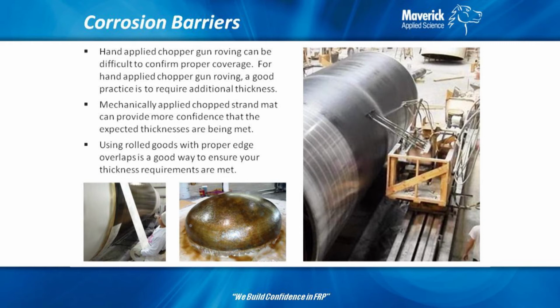If you decide to allow mechanical applied chop or even hand applied chop, it's not uncommon to require your vendor to add on a percentage, say 25%, to that corrosion barrier to ensure that you're getting the thickness of the corrosion barrier you want. So if they want a hand chop or mechanized chop, it's common to increase the thickness of the corrosion barrier a little bit to ensure you get the full coverage you want.